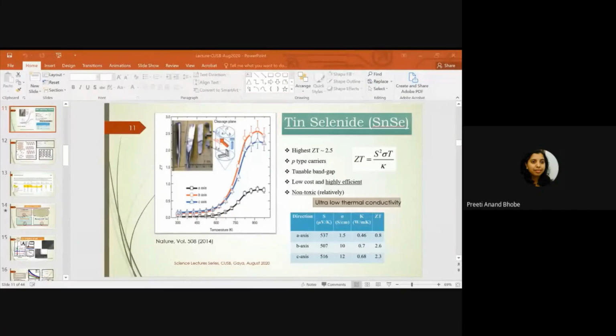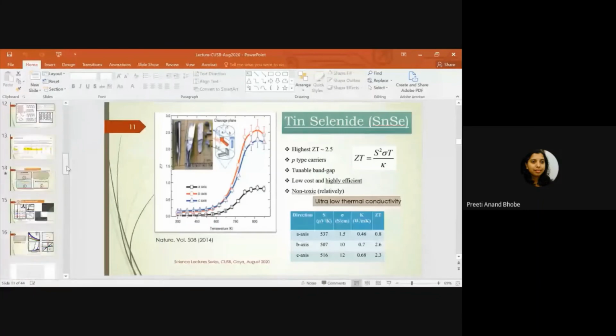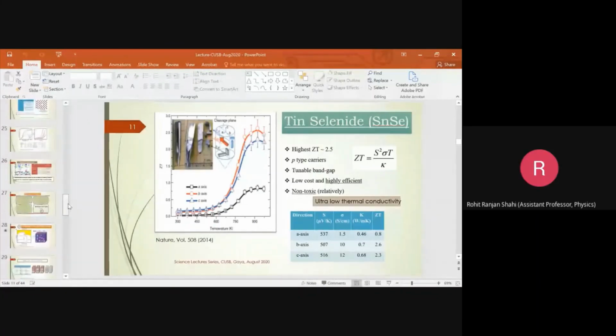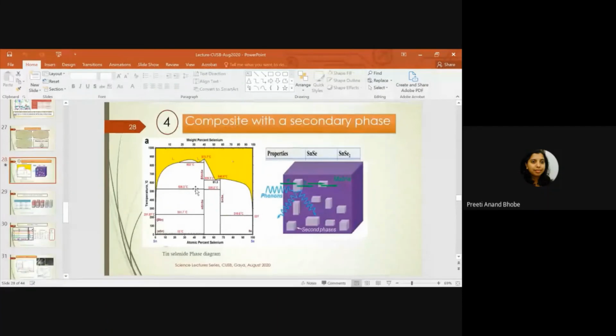But it depends, because these are low melting materials. If you have a very high current passing, what is the melting temperature of this material? The phase diagram that I had shown, because it will go from one phase to another, from SnSe to SnSe2 phase. One minute, I'll show you the phase diagram itself. In that case, SPS may create some problem. Yes, there are different phases also, alpha SnSe, beta SnSe. In this phase diagram, if you change the temperature slightly, you have to be very careful about which phase of SnSe one is talking about.